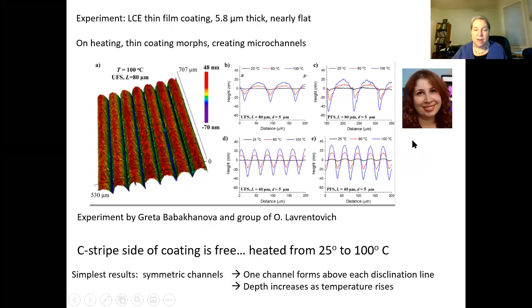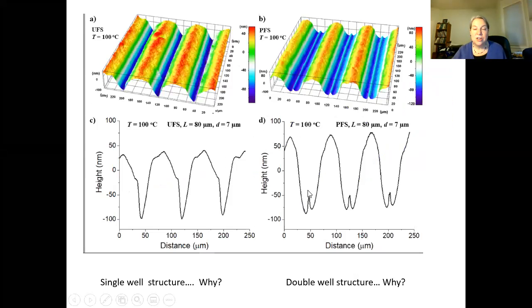This is Greta Babakhanova, who did this experimental work together with her colleagues from Oleg Lavrentovich's group. If you take a stylus and go across, the pattern goes up and down. These grooves get thicker as you change the temperature. Heating from 25 degrees up to 100 degrees, you see these beautifully symmetric channels. But sometimes she saw channels that had a double well structure, and sometimes the channels were not symmetric. Those were questions like, why would that happen?